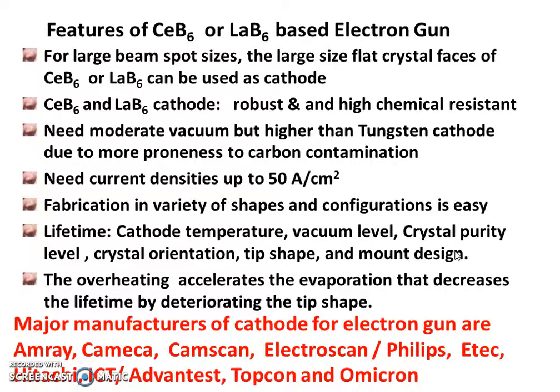These electron guns need current density up to 50 ampere per centimeter square, and fabrication is available in a variety of shapes and configurations easily. And the lifetime: the cathode temperature, vacuum level, crystal purity level, crystal orientation, tip shape and mount design, these are the features which decide the lifetime of these electron guns. The overheating accelerates the evaporation and decreases the lifetime by deteriorating the tip shape.